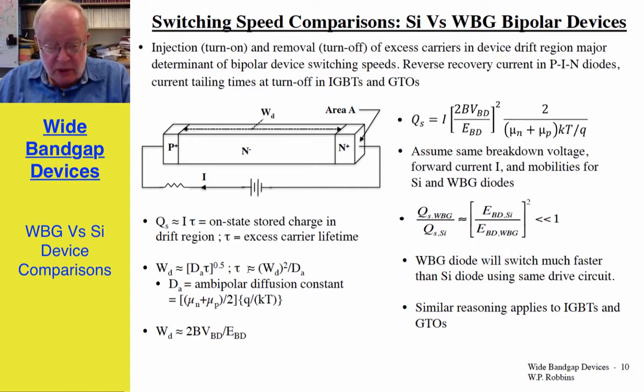If you invert this equation, I have 1 here now for the carrier lifetime, and the ambipolar diffusion constant is defined in the next equation. And the drift region length is also given here by twice the breakdown voltage divided by the breakdown field strength. Putting all that together, you can show that the excess stored charge is given by the current times these other parameters. And the thing to note is that it's proportional to the square of the breakdown voltage and 1 over the square of the breakdown field strength.